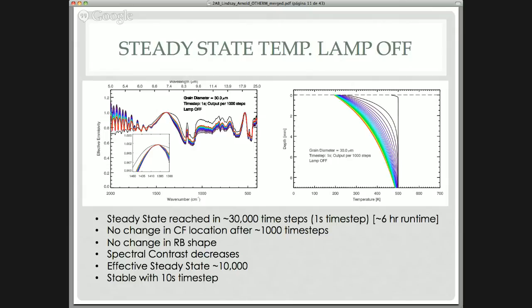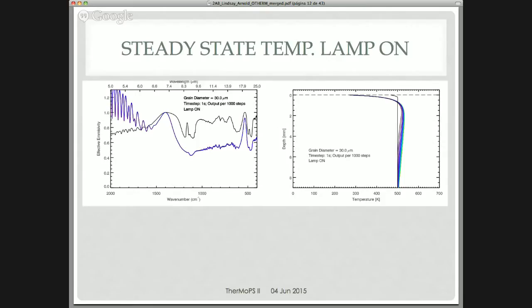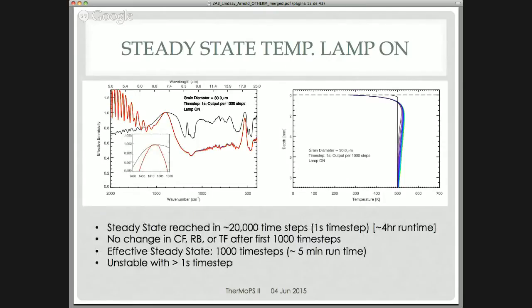This is the same experiment, except we've turned the lamp on. The one thing I want to point out is that you get this extremely steep temperature gradient in the top millimeter, and it doesn't take very long for it to be established. And once it's established, it doesn't matter how long you integrate, your emissivities, at least according to the model, lock in, and you see essentially no change. That indicates that maybe this uppermost steep temperature gradient is one of the most important factors. This also means that if we're doing simulations with the lamp on, or daytime measurements, then you don't have to integrate very long, so we can do these computations very, very quickly.